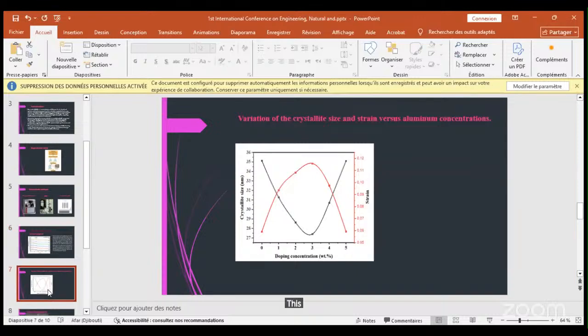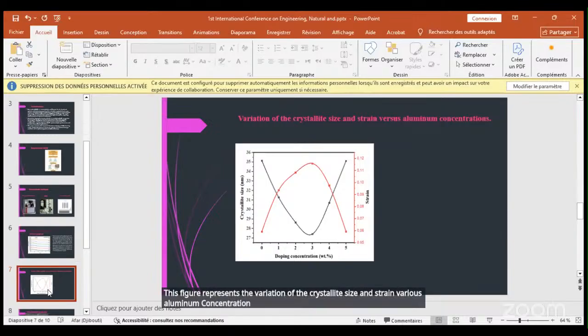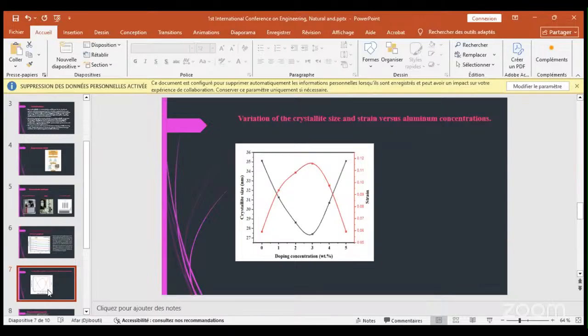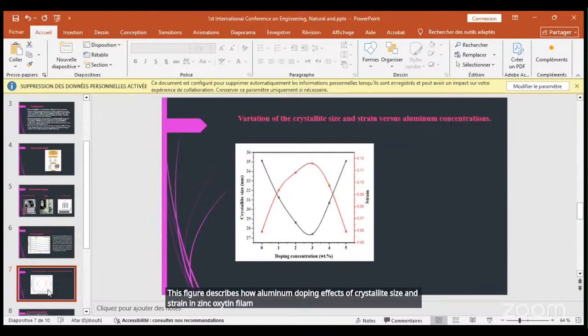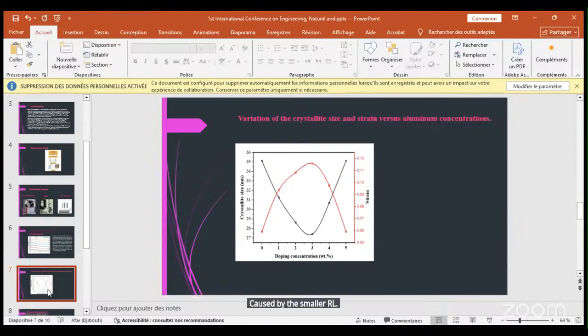This figure represents the variation of the crystallite size and strain with various aluminum concentrations. This figure describes how aluminum doping affects crystallite size and strain in zinc oxide thin films. Initially, increasing aluminum concentration up to 3% reduces the crystallite size from 35 nanometers to 27 nanometers due to the lattice contraction caused by the smaller aluminum ion replacing zinc Zn2+. Beyond 3%,